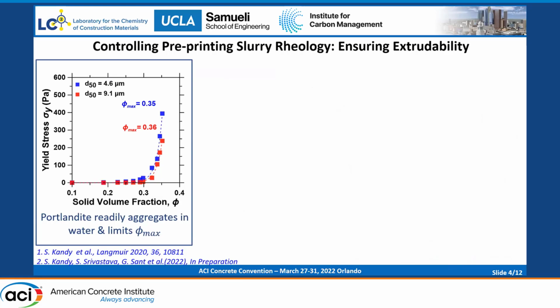First and foremost, we need to have an optimal pre-printing rheology for these suspensions. That means we should have a high solid content and an optimal flowability. What is shown here is the evolution of yield stress as a function of solid volume fraction in the suspension. This is important in suspensions like portlandite. As you can see here, when we cross a volume fraction close to 30%, there's a significant increase in the yield stress and the viscosity of the suspensions.